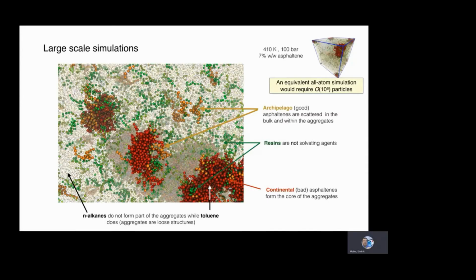Resins, which are intermediately small molecules and, in some probably wrong theories, are described as peptizing agents that could solubilize the clusters, are seen to be very well spread and very well diluted in the system. Toluene is seen to form part of these clusters, while alkanes, for example, are seen to stay away from the clusters. To perform this simulation with an all-atom model would have required in the order of several millions of particles, something which is well beyond what we would normally want to do for the time scales that were needed to see the aggregation.